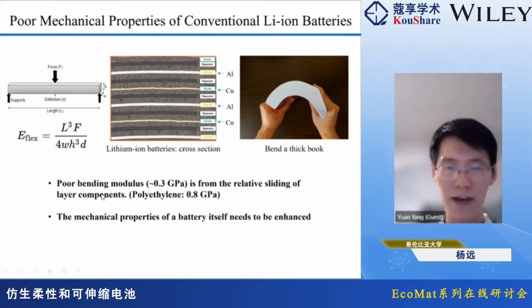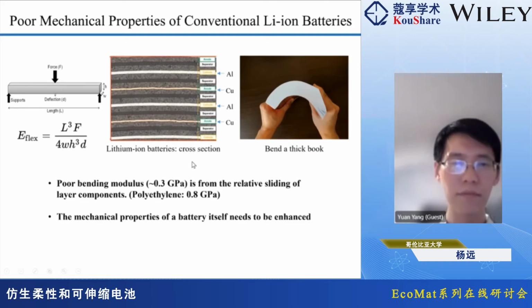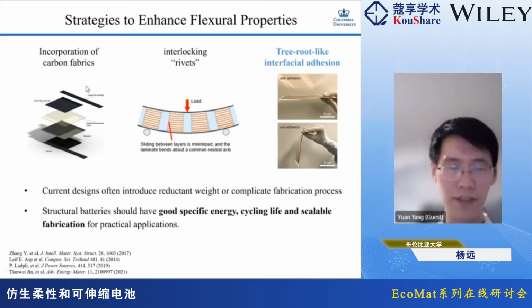So we do need to improve the mechanical properties of batteries and reduce the relative sliding between different layers inside. There have been some previous strategies. For example, we can put carbon fabric inside. Carbon fabric is made of carbon fiber, so it's a very strong material. But the problem is that carbon fiber doesn't have a good electrochemical performance compared to, for example, graphite, and it also increases the weight significantly.